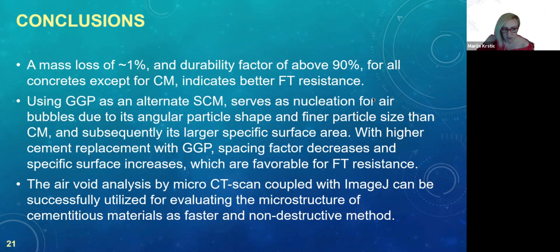The air void analysis by micro CT scan coupled with ImageJ can be successfully used because it's a non-destructive method, and preparation of samples takes less time, and it shows that results are very comparable.